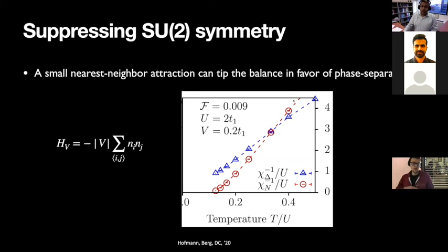And immediately you find that, in fact, the system wants to phase separate instead of becoming a superconductor. So the red curve is the inverse charge compressibility, which goes to 0, meaning the charge compressibility diverges. And so this is the point at which the system becomes phase separated instead of being a superconductor. Okay, so again, this is something beyond the reach of BCS mean field theory.